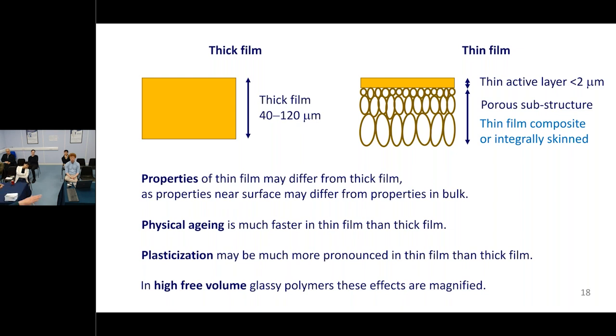In our case, it's often about 2 microns, but you can be aiming for less than a micron, even at just a few nanometers. And what we've measured in the thick film is not necessarily the same as what happens in the thin film, particularly dealing with something like a glassy polymer. So the properties of the polymer actually are different near a surface to in the bulk. As you go from a relatively thick film to a very thin film, the surface effects start to dominate.